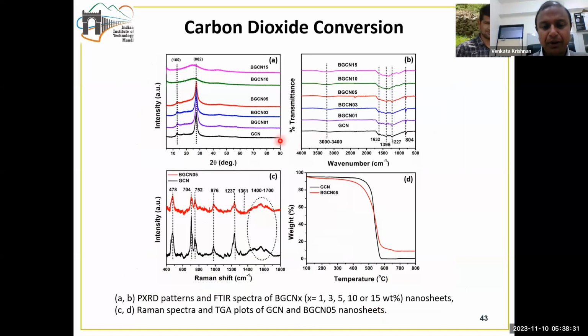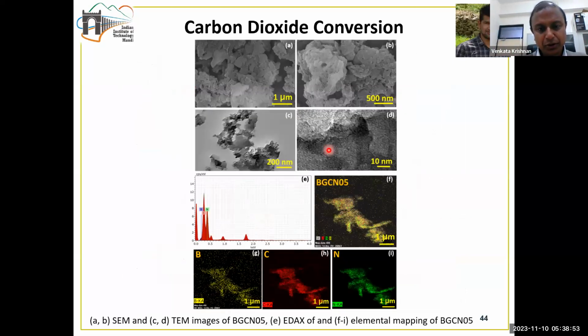And we prepared the catalyst in varying percentages of boron ranging from 1 weight percent to 15 weight percent. And we have done a detailed analysis of the catalyst using powder X-ray diffraction, FTIR spectroscopy, Raman spectroscopy, and also the thermogravimetric analysis to study whether the catalyst is formed according to our expectations, what are the functional groups involved, and what is the thermal stability of the catalyst. Subsequently, we also did the morphological analysis using SEM and TEM techniques coupled with the elemental mapping and EDAX technique, which can clearly show that this catalyst is forming a sheet type of structure, and also this is the elemental distribution on the catalyst surface.